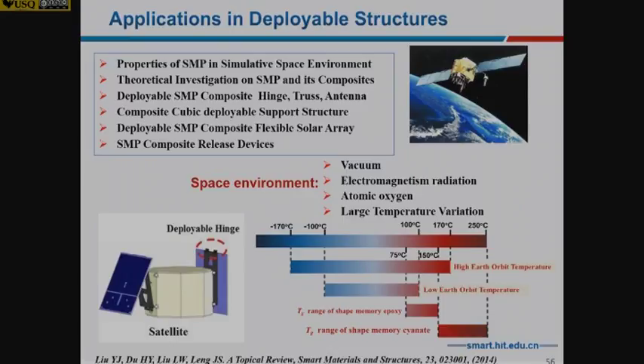For epoxy, the temperature range can go up to 150. So that one can be used for low Earth orbit, which is normally -100 to 100, and our epoxy is beyond that range. But that epoxy cannot be used for high Earth orbit, because in high Earth orbit the temperature is from -170 to 170. That's why we develop another one with higher Tg, which is cyanate ester, up to 250.